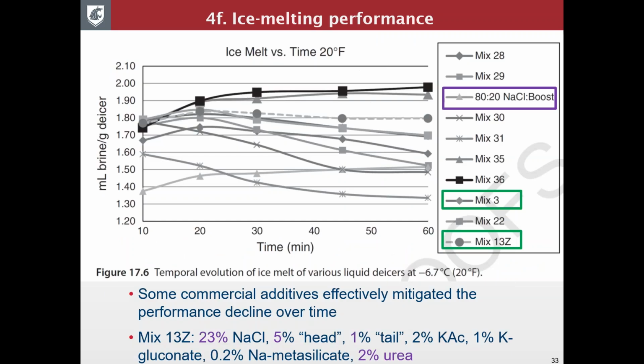Now, one thing we did detect was a decline of performance in some liquid formulations because of evaporation of this head and tail. So we further experimented with other additives, for instance, the use of urea. It's kind of hard to see here, but the best one had a stable performance over time because of the use of urea and other additives. But I want to highlight mix 13Z because later on we tested more of that. In this case, we bumped the sodium chloride concentration back to 23% and used 2% urea, and the performance was much better than the sodium chloride Boost blend.